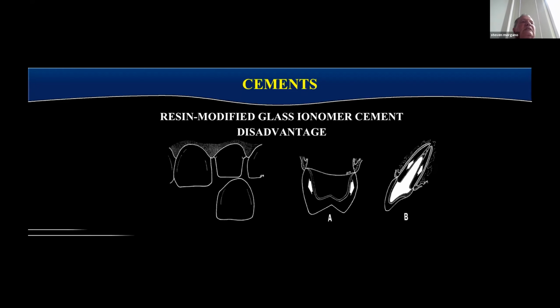Now, Gordon Christensen did a study. He filled glass pipettes with resin-modified glass ionomer cement and just left them in water. And eventually all the pipettes, the glass, fractured. Now, it took months for it to happen, but eventually they all fractured. So no one's ever proven that this cement can cause the ceramic crown or the root to fracture. But why take a chance when we have other cements that are just as good?